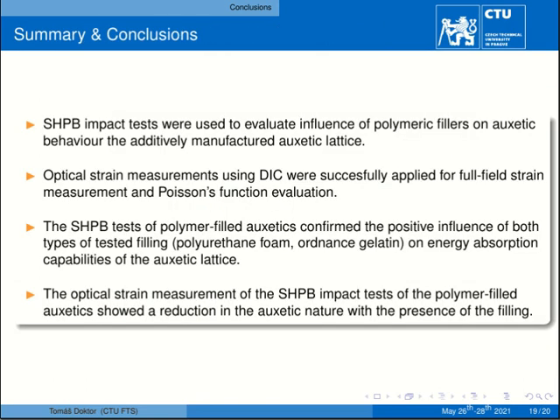Now briefly to the conclusion. The SHPB apparatus in the Laboratory of High Strain Rate Phenomena and Dynamic Testing of the Czech Technical University in Prague was used to evaluate the influence of the polymeric fillers on the auxetic behavior of additively manufactured auxetic lattices. The optical strain measurement using a custom DIC tool was successfully applied for full field strain measurement and enables the Poisson's function evaluation.